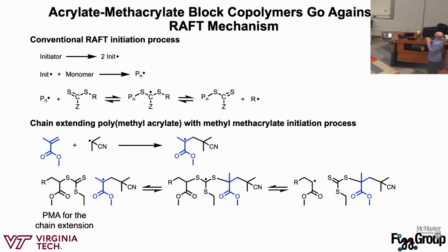So you're going to get an oligomer of methyl methacrylate, and then this oligomer of methyl methacrylate radical is going to have to add into this polymethyl acrylate that you're actually trying to chain extend. You want to go through this chain transfer process and kick off this methyl acrylate so that you can actually chain extend all your polymers. Does anyone have any ideas why this wouldn't work? I was putting people on the spot for this. I usually put faculty on the spot for this because it's more fun for me. Catherine?